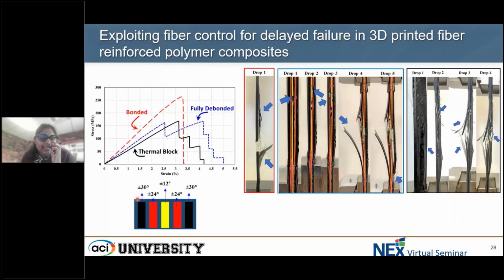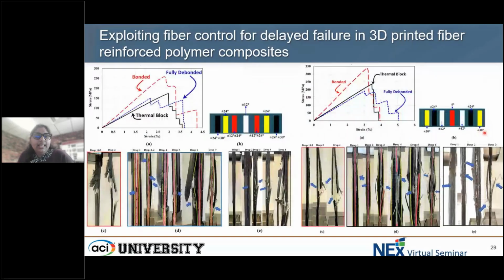In this case, if you look at the bonded, one drop, brittle failure, completely broken composite. In the blue color, which is this box here, drops 1 through 5, we noticed sequential damage in the layers, resulting in failure of the entire composite. And in this black box here, you've seen some drops that were able to completely fail the composite, but in a sequential manner. In designs 2 and 3 also we've seen similar kinds of behaviors.